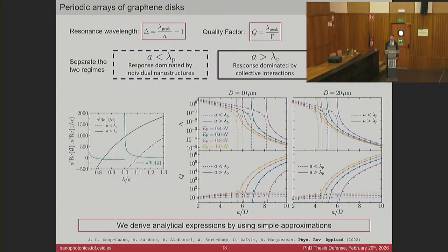I mean, it depends on the material. It does depend. If you choose the same parameters but two different materials, the material that has the higher non-radiative losses is going to have a resonance with a lower quality factor. But you can always say, okay, but I go to larger periods until my quality factor is as large as I want. You're right that I could choose a different material, but in this case, what we are exploring is not really different materials, but by just taking something that we know, for example, silver, and exploring new configurations like this bipartite array or the excitation with the Gaussian beams. Trying to change one thing at a time.